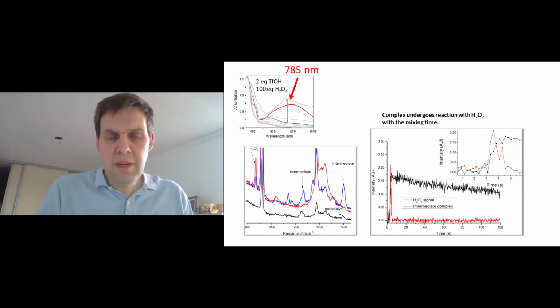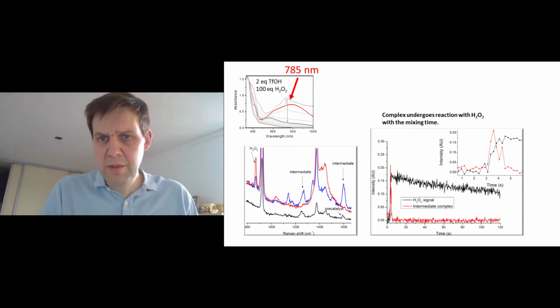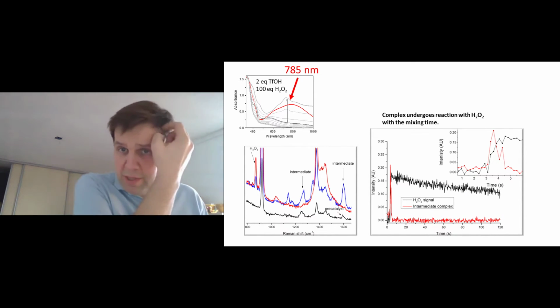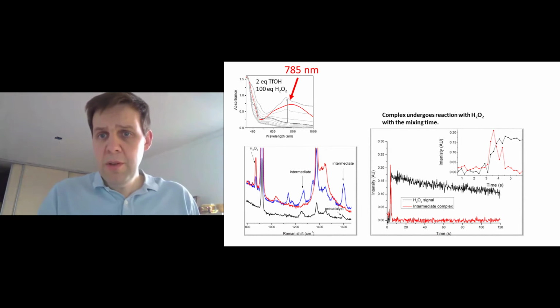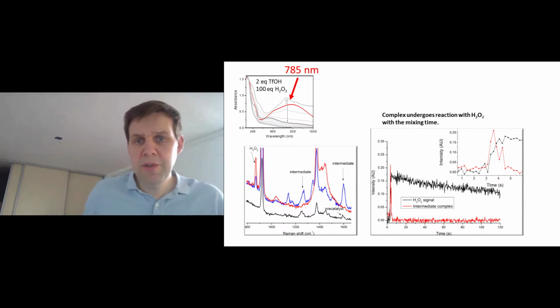And that's about as high a time resolution as we've gone so far with this system. We can go faster, actually. It is possible to go faster with reasonably low power lasers. But what you notice is the spectrum is very jumpy. And you see there's an increase and a decrease in the signal. That's not because of noise in the system.